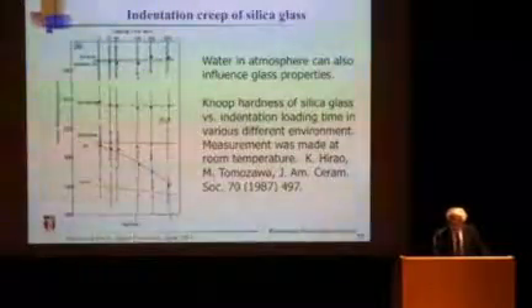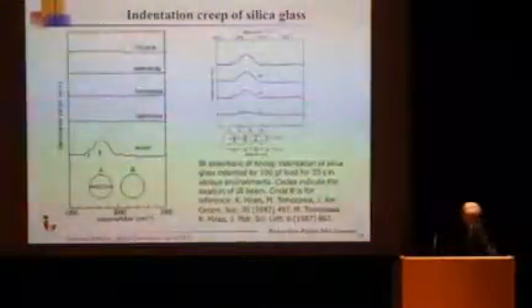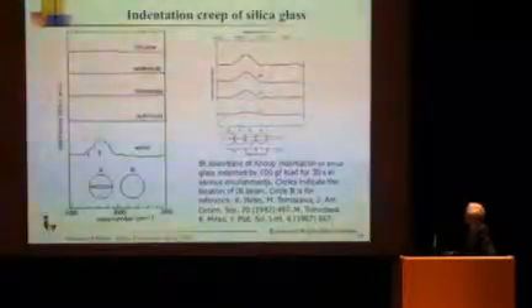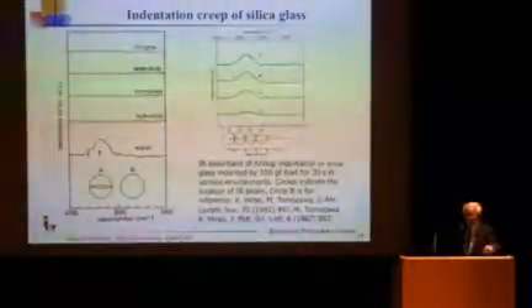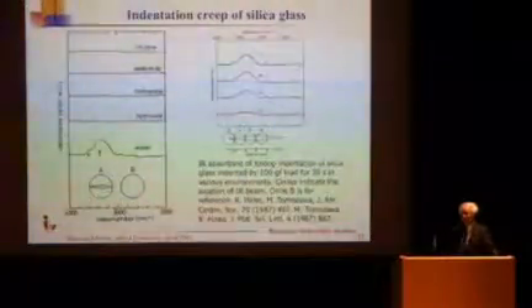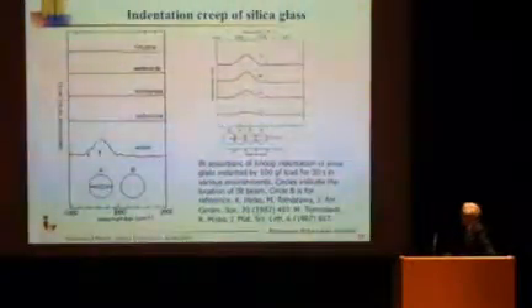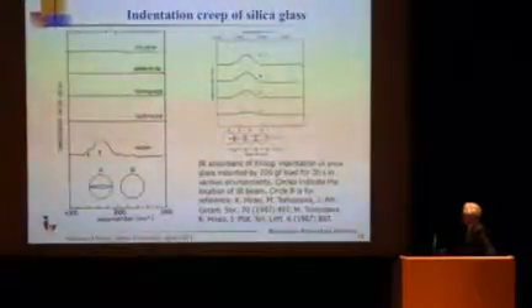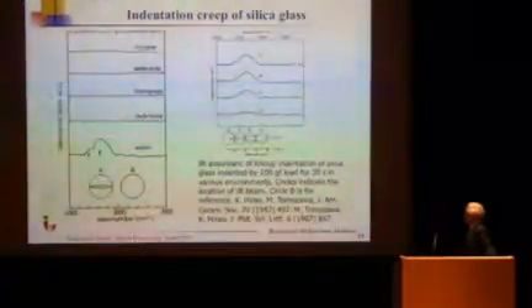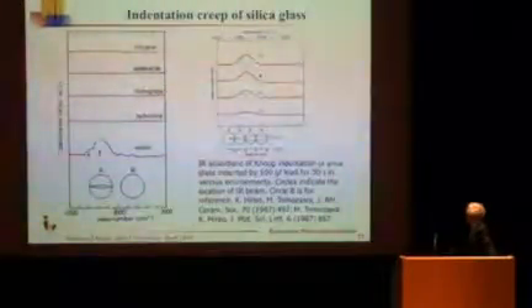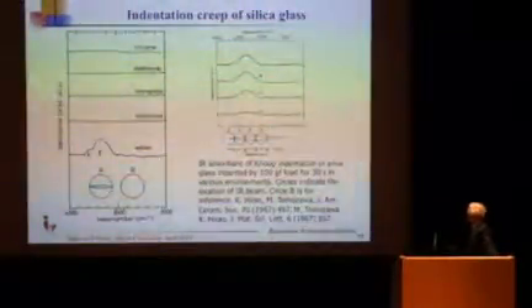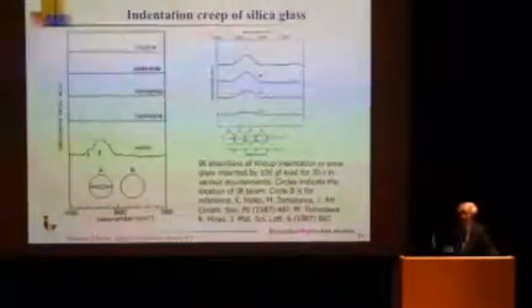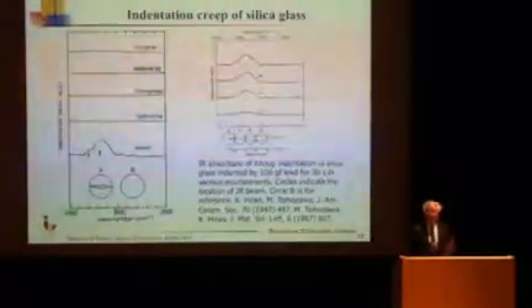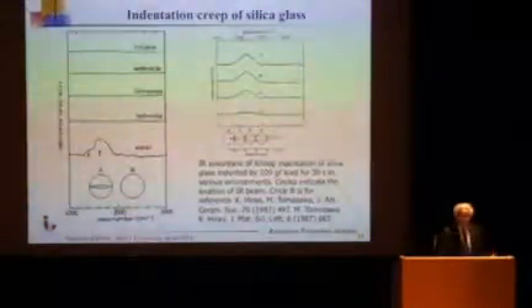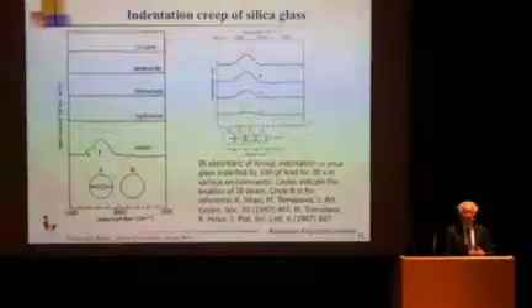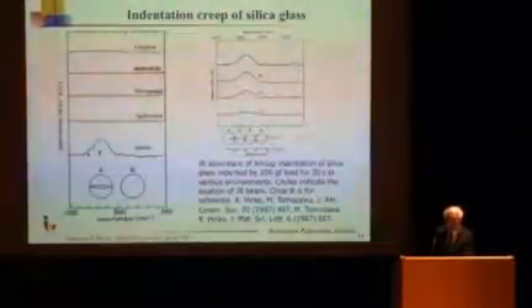It has been well known in the community, but what we found is that the drop is due to water entry. Water is entering into the glass while you are doing indentation work. And we show this by the infrared peak formation before and after indentation. If you look more carefully, there's more water here than here. So definitely while you're measuring hardness at room temperature in air with a slight amount of moisture around, the hardness decreases with time. That's because water is getting into the glass.